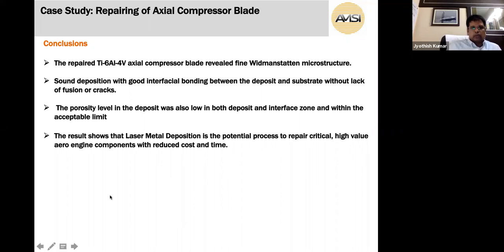Yeah. And the porosity level in the deposit was also very low in both the deposit and the interface zone, and within the acceptable limit. Yeah, there are certain limits of porosity which you can accept, and up to 1%, 2% porosity is acceptable. Okay, so the deposition process was done within the acceptable limit, and the porosity level was very, very low, and it was in the acceptable limit for different applications.